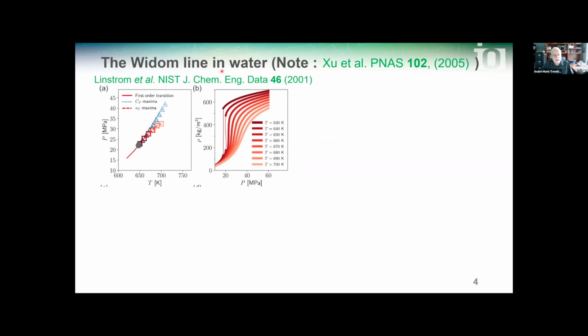The name Widom line, that is in the title, was suggested in 2005 by the Stanley Group. Here is what it looks like in water. You have a first-order transition in the pressure-temperature phase diagram that ends at the critical point. If you take constant temperature cuts as a function of pressure, you find a low temperature jump, obviously, that we all know, and a higher temperature crossover. Strictly speaking, the Widom line above the critical point is the line where various extrema of thermodynamic quantities converge towards the critical point.